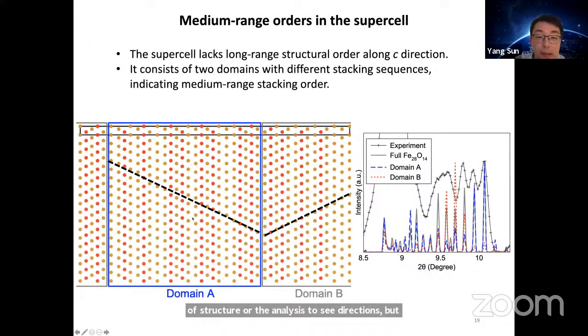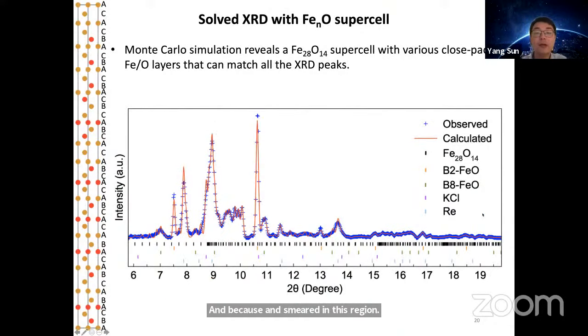But when we look in detail at this stacking, we can identify domains. This dashed line shows the direction of the domain boundaries. The domain size is around 20 atomic layers, or around 30 angstrom, and each has a different stacking sequence. So this forms a kind of medium-range order, and it contributes differently to the XRD. As you can see, if we isolate domain A and calculate its XRD, it mainly contributes these two peaks. Domain B contributes somewhere here. The combination of A and B and their interference give rise to these multiple peaks smeared in this region. Finally, with experimental refinement, this structural model well describes the experiment.